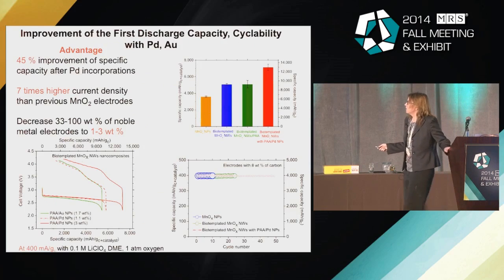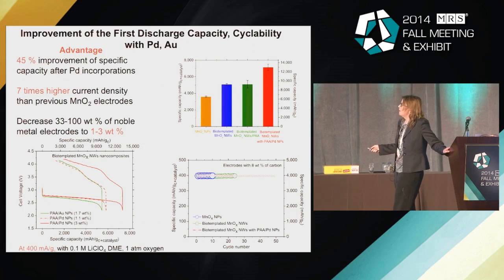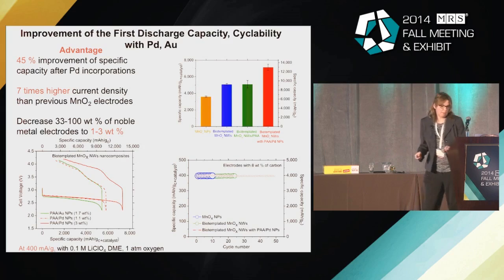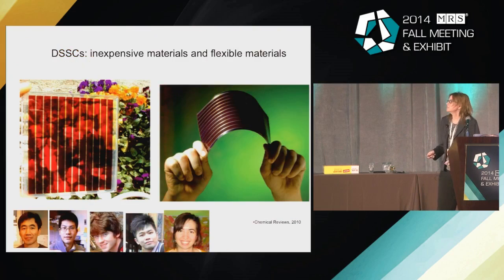And so this is manganese oxide nanoparticles. This is biotemplated manganese oxide nanowires. And this is biotemplated manganese oxide with the palladium. And you can see that we get a 45% improvement of specific capacity when you have this whole complex together. And you have a 7 times higher current density. And it only has a small amount of the noble metal, 1 to 3% for this performance.